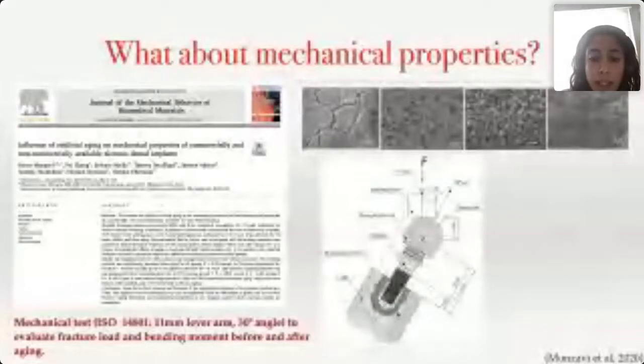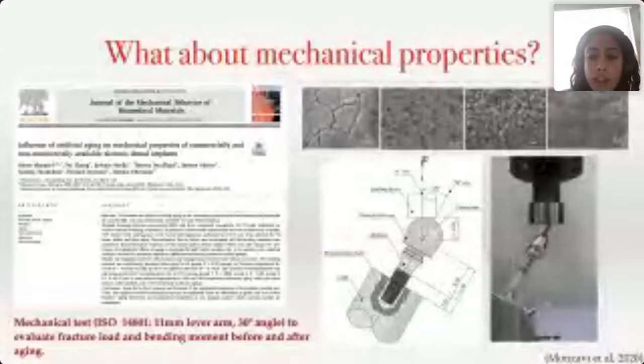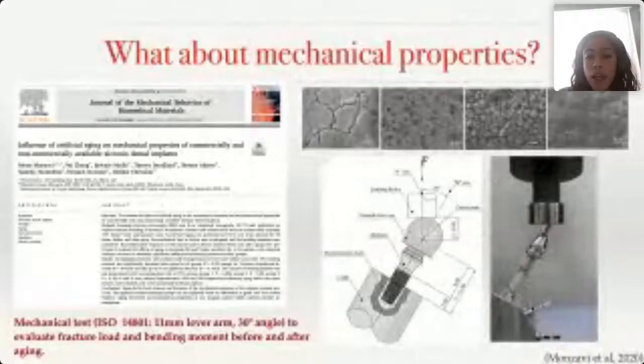These implants were mounted at a 30-degree angle with an 11mm lever arm, and a load was applied until it fractured. We did this before and after artificially aging these implants, and then calculated the bending moment before and after for each group.